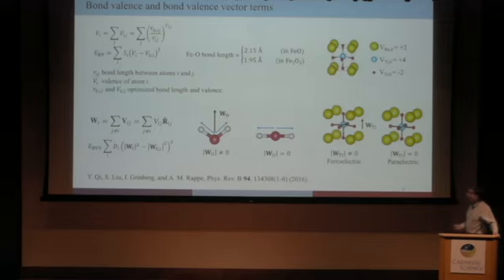Okay, so this is a little bit more in depth about these potentials. So as I was mentioning, this is the way we calculate the bond valence. It's the sum of the individual bond valences, and that is an inverse power law of the distance between each atom and its nearest neighbors. And then we get the energy of the bond valence as its deviation from its prototypical valence.